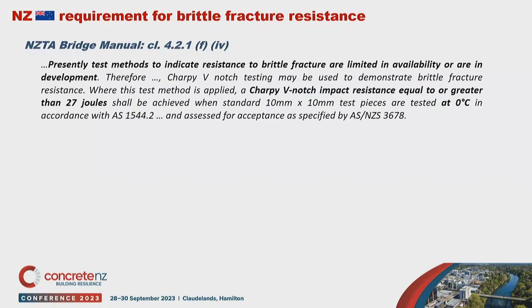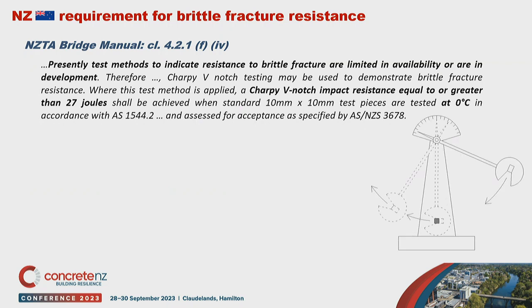So with this, we look at the other standards available, like the NZTA Bridge Manual. Generally what happens with the Bridge Manual is that it tries to follow 3101 where possible, but sometimes it extends the requirement and adds something extra. In this case, we have some indication for how to test for brittle fracture resistance. However, this is a requirement that is specific to the material of the coupler itself. So the indication is to perform a Charpy V-notch impact test on a little sample that needs to be cut out from the coupler.